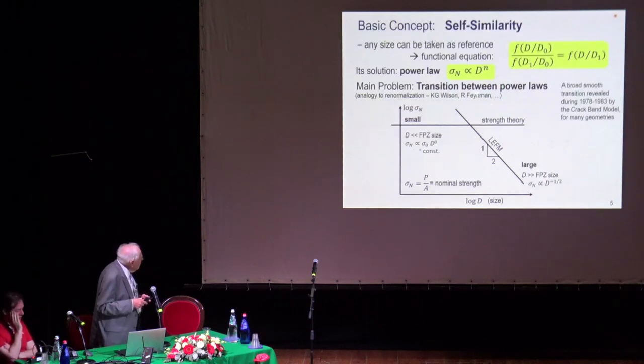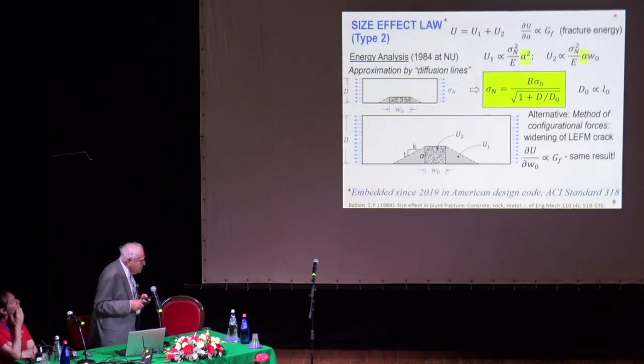and engineering. Now, using simple arguments, including, for example, dimensional analysis, you quickly conclude the power law for strength theory must have exponent zero, a horizontal line if you plot logarithm of nominal strength versus logarithm of the size. On the other hand, for linear elastic fracture mechanics, because of the dimension of fracture energy, energy per surface area matters, not per unit volume, you conclude the other asymptote must be 1/2. So that's obtained immediately. But the question is the transition, which actually takes in most structures about 3 orders of